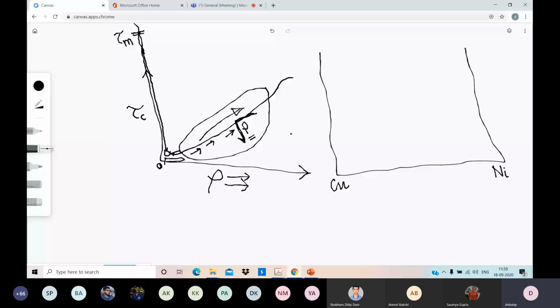But what is this phenomenon called, when dislocation density is high and the stress requirement to cause a certain amount of deformation is high? Strain hardening. That's why your stress-strain curves look like this: to get a certain amount of deformation, you need to apply higher and higher stress. The reason behind strain hardening is that more and more dislocations come and interact. They develop a spider-net kind of structure where movement of any one dislocation becomes more difficult.